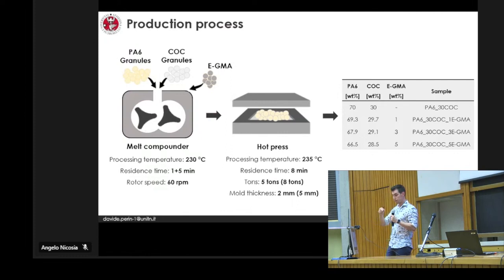laboratory? It has a small size of material, like 50 grams per size. But this was the best option for us because we also have a monoscrew, a bi-screw extruder, but the residence time is too low. We are talking about 30 seconds to 1 minute. The time here is mainly dictated by the reaction, because once we add the compatibilizer, we need to give it the time to react. So 5 minutes was the bare minimum in order to stabilize the torque inside the compounder. So that's why I selected this.